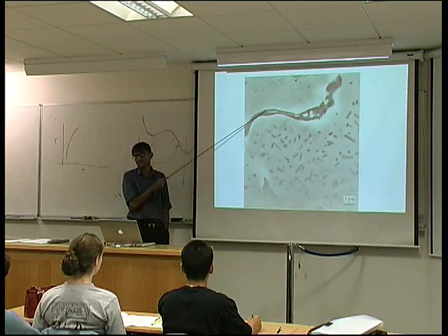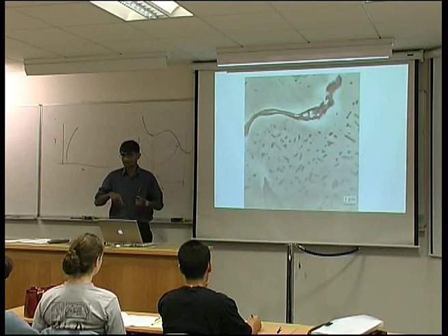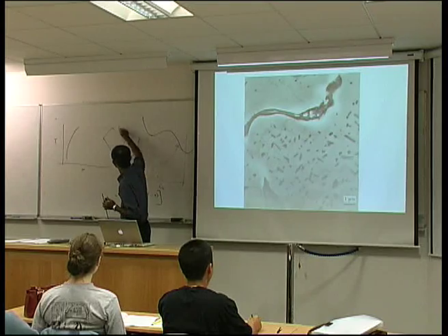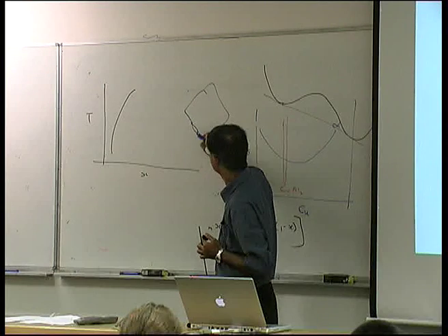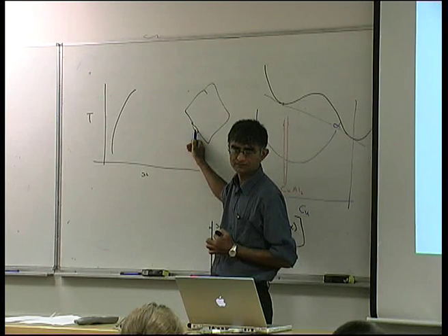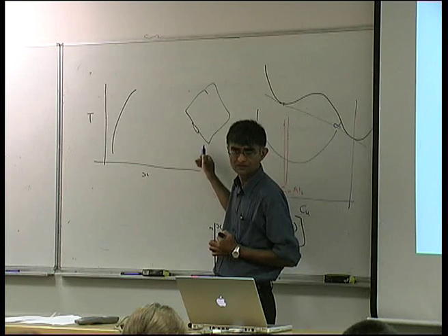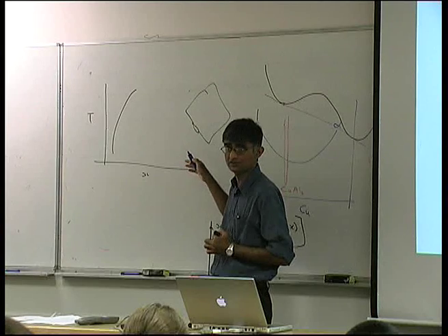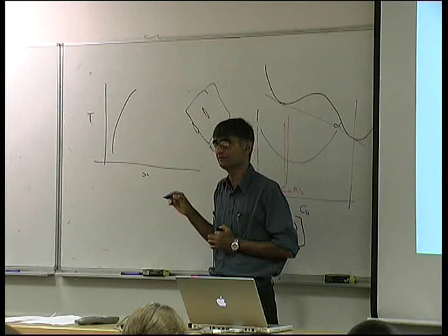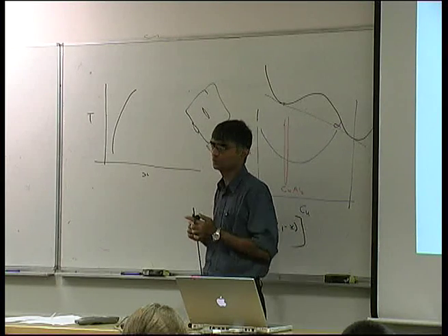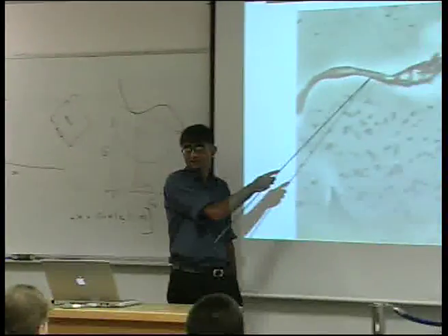Well, nucleation first happens at a grain boundary, which is a very strong defect. And imagine that you have a grain boundary here. And if I have a precipitate over here, then there is a gain because I've destroyed some of that defect in the process of forming that particle. I've destroyed some of the boundary, correct? And that's the reason why grain boundaries are very good nucleation sites. If I form the same precipitate here, I don't have that gain. I haven't destroyed some of the defect, right? So it's much easier to form at the boundary than inside the grain. So these particles form first, and...